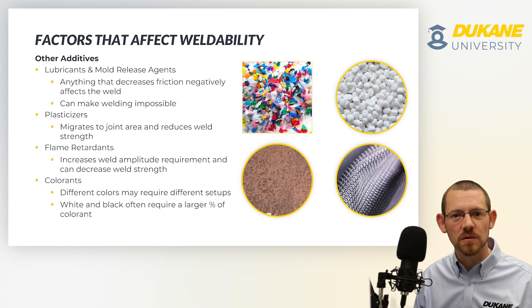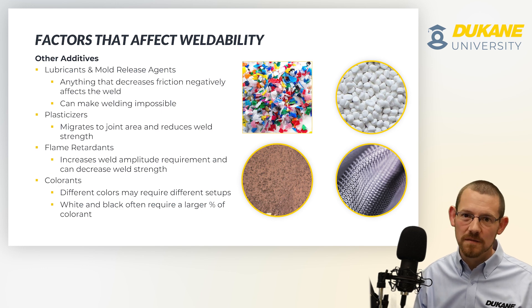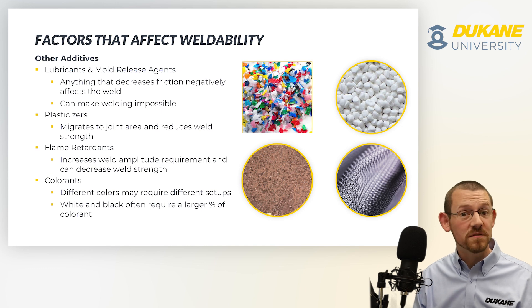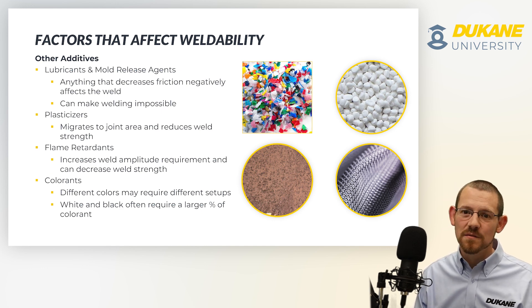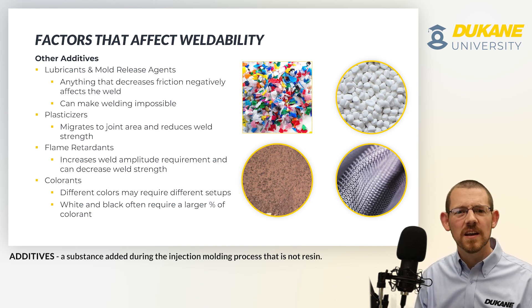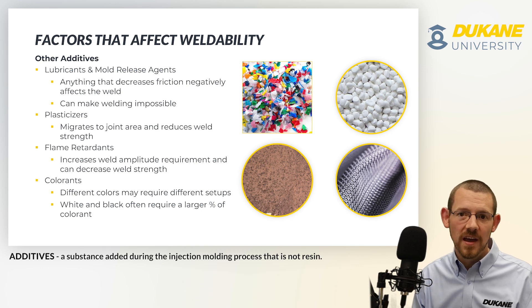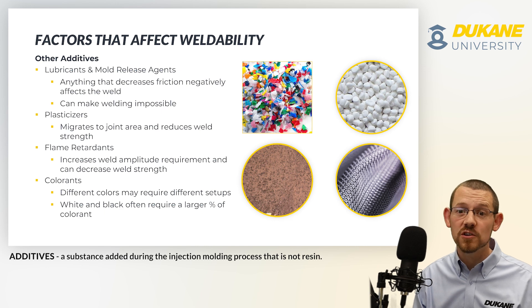There are a number of other additives that will impact your ultrasonic weld quality. Lubricants or mold release agents reduce our ability to weld, since ultrasonic welding relies on friction to generate heat — anything that makes your part more lubricated makes it more difficult to process. Plasticizers increase ductility but tend to migrate directly to the weld joint, often reducing the strength of your parts. Flame retardants raise the melt temperature, so adding one will increase the energy and amplitude your ultrasonic system needs to deliver — and if you do that after you've already spec'd your equipment and tooling, you might have insufficient capability to handle that change.